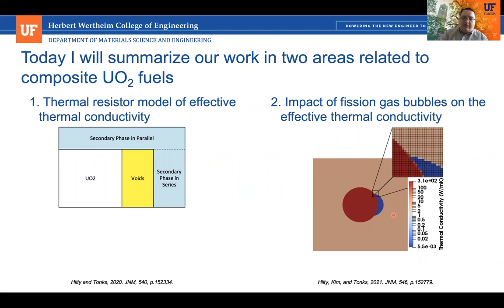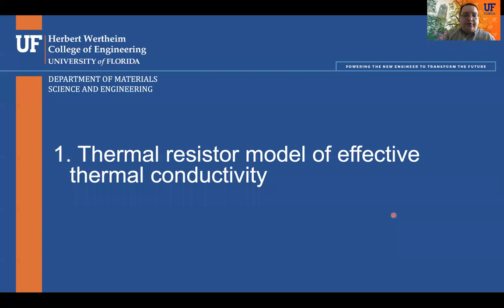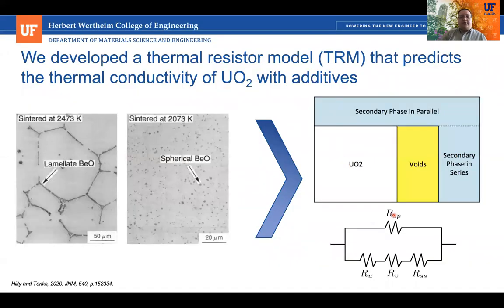First off, we've developed a simple thermal resistor model that can capture a range of different types of composite fuels and estimate the effective thermal conductivity, and it takes into account the microstructure of the fuel. And in the other case, we've looked at these composite fuels, but specifically at the impact of fission gas on their improved thermal conductivity. So first, I'm going to talk about our simple thermal resistor model.